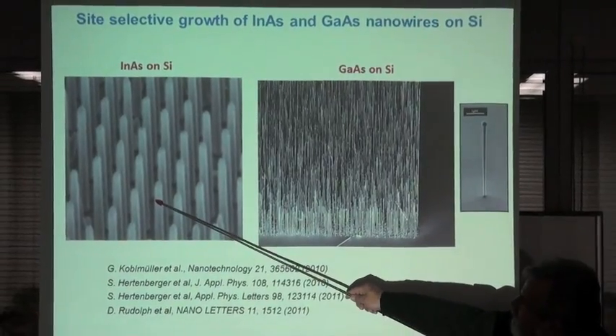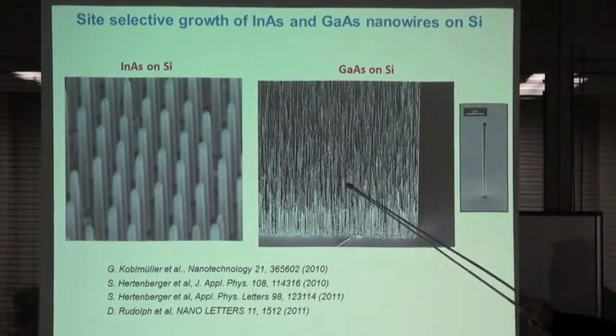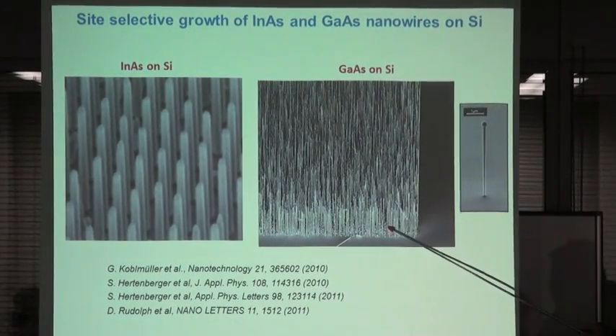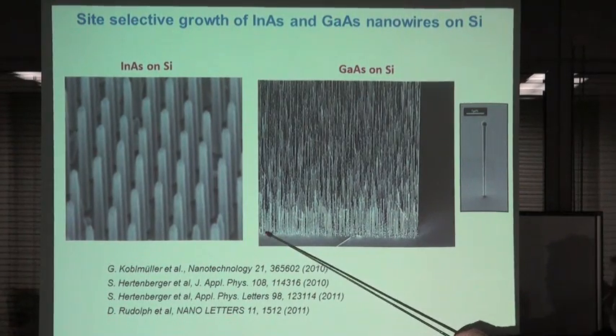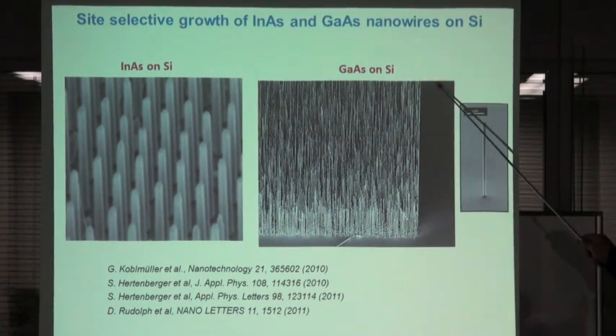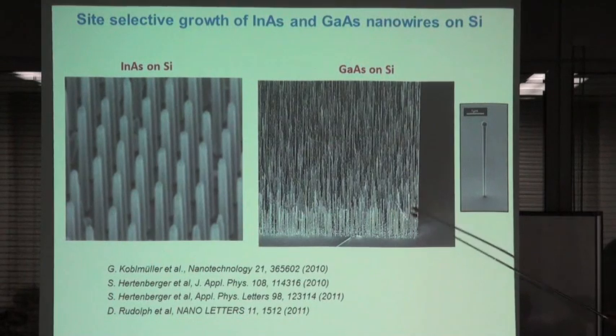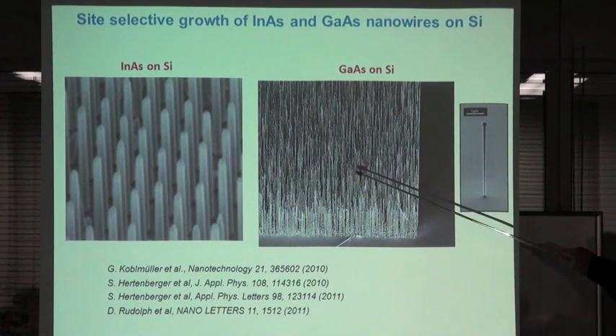This is again comparing indium arsenide on silicon and gallium arsenide. You see the yield is not as good. This is a patterned silicon substrate here. There are no holes outside, but we can also get rid of all these clusters which we normally have on such a surface. We have them in here. They nucleate partly also in the holes. And the yield here is only something like 50% of wires.